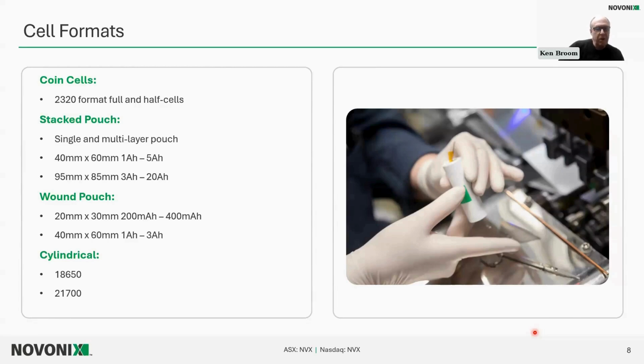For wound pouch cells, we have again two formats. The smaller ones are in the milliamp hour range. The larger ones get up to about 3 amp hours. And for cylindricals, we do 18650s and 21700s.